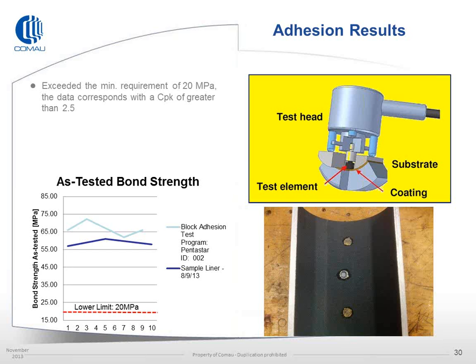One of the issues most people have is how do we assure adhesion. As we've gone through and done a lot of mechanical testing, we can find that in our test samples using a standard pull gauge, we can pull up an adhesion sample right off the coating and measure the mechanical bond strength using a simple button that's glued to the surface.